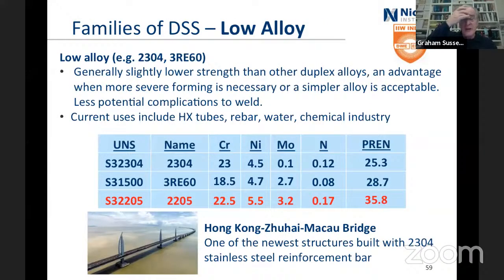So looking at the low alloys one, the 2304, or this is a proprietary grade, lower strength than the other duplexes, which is nice if you've got to do really severe forming. Less potential complications for the welding because you've got not a lot of moly in it and not big heaps of chromium, and PREs in the moderate range. Heat exchanger tubes, rebar, water, chemical industry, and this bridge.